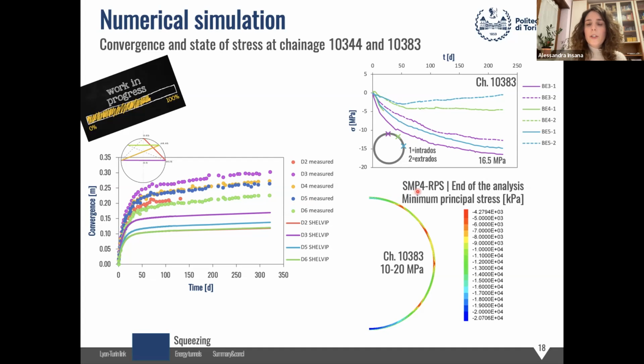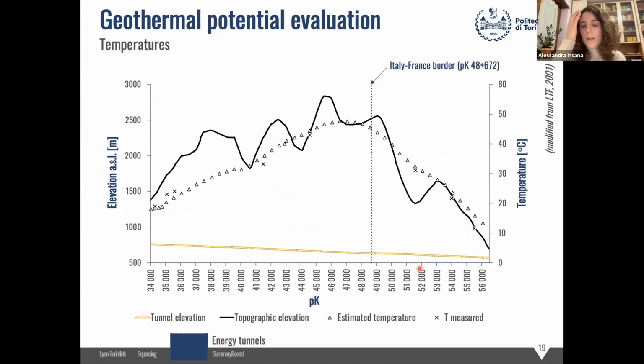Still, from the stress point of view, here on top you see a picture of the stresses in these points measured in the shotcrete. They reach up to 16.5 megapascal. We are in another chainage actually. And in the model, we are between 10 and 20 megapascal. So from the stress point of view, it works a bit better, but it's still ongoing work. So this was the first part.